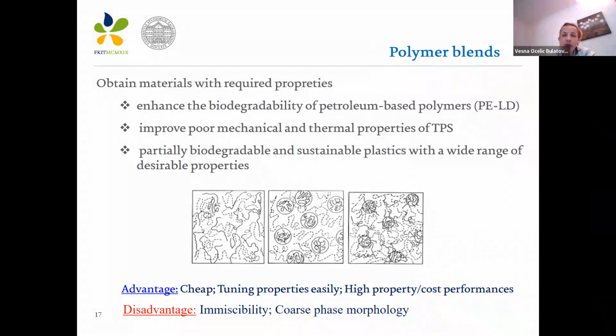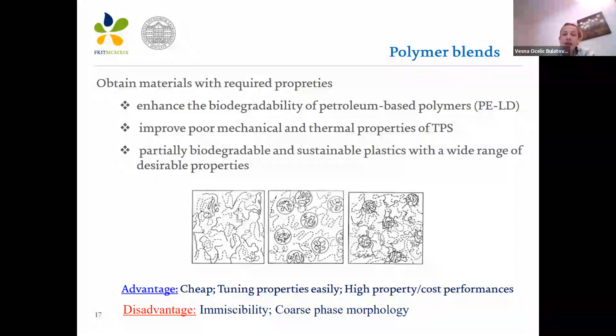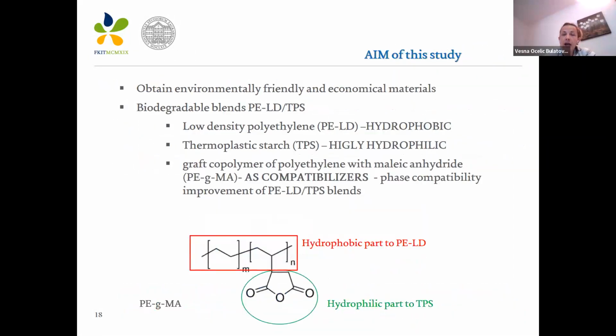As I said before, blending polymers is the most effective way to obtain materials with the required properties. So blending a conventional polymer with thermoplastic starch is a significant way to overcome the limitations of the individual materials, thermoplastic starch and low-density polyethylene. It also improves the weak mechanical and thermal properties of TPS, while on the other hand, the biodegradability of such a blend is enhanced. The aim of our research is to obtain environmentally friendly and economical, which is very important, economical, biodegradable blends of low density polyethylene and thermoplastic starch.